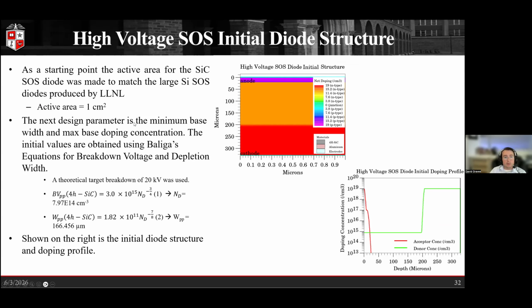Following that, the next design parameter, again, would be the minimum base width and max doping concentration using the Baliga equations for that, intending to get a theoretical breakdown voltage of 20 kV. We found that our base doping concentration should be about 8 times 10 to the 14 per centimeter cubed. And our parallel plane width should be about 166.5 microns wide. And so using that, we came up with this initial doping profile.